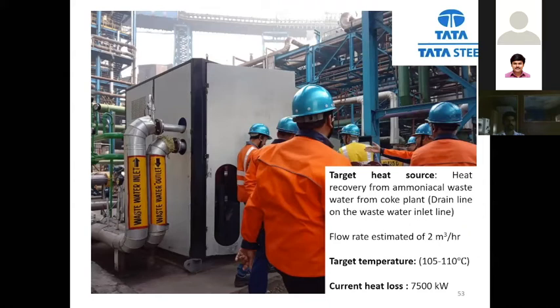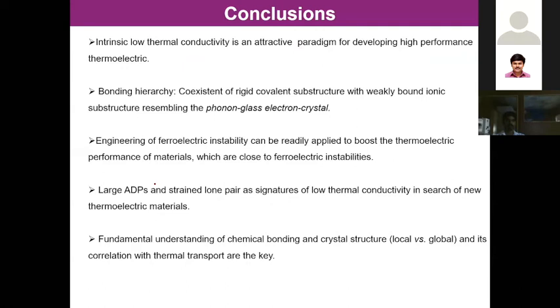With that, I conclude that intrinsically low thermal conductivity is an attractive paradigm for developing high performance thermoelectrics. We can create low thermal conductivity by playing with chemical bonding and lattice dynamics, basically coexisting rigid and covalent substructures in a single material. So we can have phonon glass electron crystal type solids, and we can also engineer ferroelectric instability in a thermoelectric material. I showed you some of the examples.